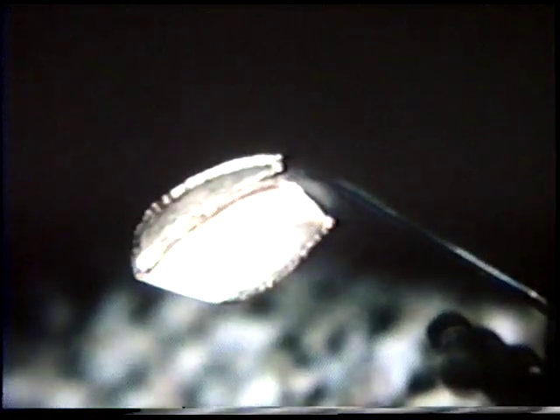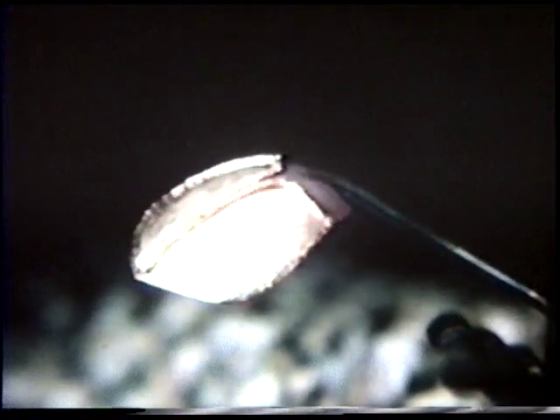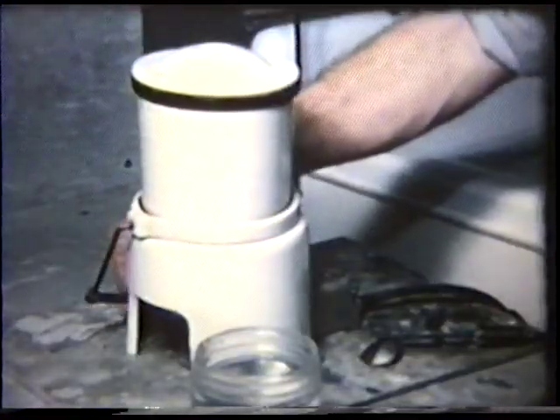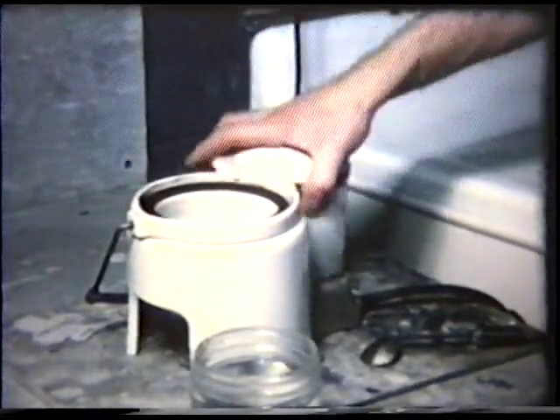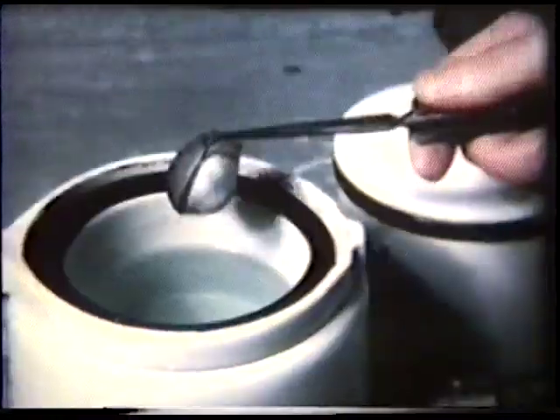To fuse these rectangles onto the surface, the piece is held in a reducing flame with stainless steel tweezers. The reducing flame turns the copper oxide on the surface to an infinitesimal film of pure copper at a temperature around 1600 degrees. This copper causes the surface of the gold to melt and combine with the copper to form a minute quantity of solder which flows along the joint and fuses the pieces together. Since the temperature is close to the 1700 degree melting point of the 18-karat gold, the work must be brought up to temperature slowly and evenly to prevent overheating any section, and may take as long as 5 or 10 minutes.